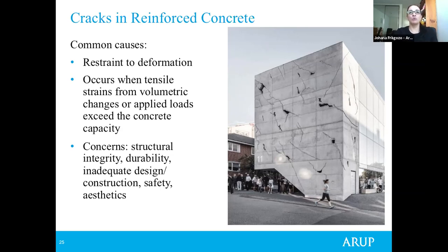It could be due to thermal overstresses, and exposed facade concrete cracks are most usually the result of corrosion of the reinforcing bars. The reinforcing bars have not been sufficiently protected by the depth of concrete cover and are likely to corrode due to carbonation or to chloride elements.